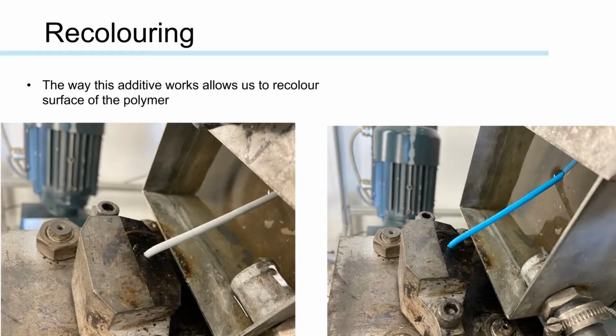The way the additive works, by occupying the boundary layer between the extrusion equipment and the melt phase, allows us to actually recolor the surface of the polymer. We can select the thickness of that boundary layer, and by adding master batch with an affinity to the additive that's held within the carrier, it allows us to recolor the polymer.